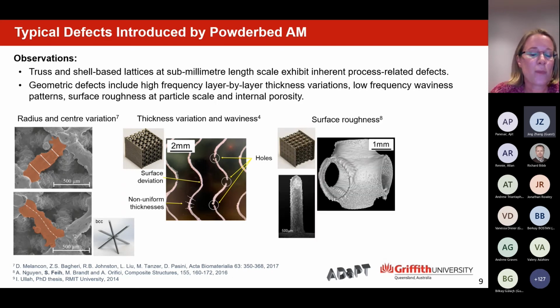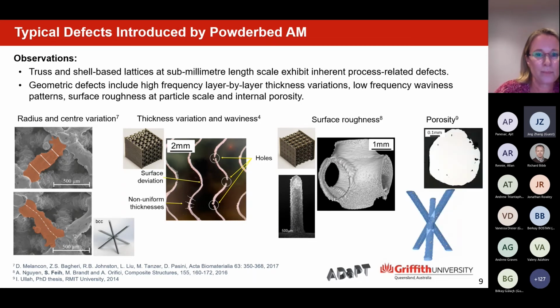We can see surface roughness. So again, for powder bed processes, our average particle diameter is in the order of 30 to 50 micron. Now, again, these particles attach partially to the surfaces in the melt pool. And you can imagine that when you push the wall thickness down to the order of 100 to 150 micrometer, those particles and their roughness start to contribute significantly to the weight of the structure without actually helping with the mechanical performance. If we have structures that are 1 millimeter or 1.5 millimeter thick, this doesn't really matter. But if we push it down to 100 micrometer, it becomes a very important aspect. And lastly, some porosity as well, which is always inherent to the printing process. It's small, but it's still present.